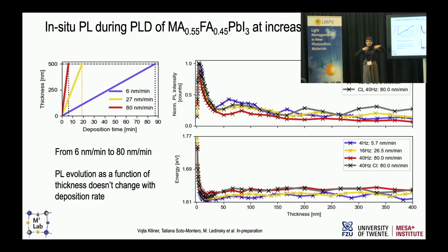So what limits? I think in terms of material quality, it will be the nucleation and growth. You have a lot of nuclei, and if you do it too fast, at some point the grain will be too small. So you might need to play with temperature and other things. Temperature is also a challenge, because if you have temperature and your molecules arrive, they will actually go away. So you might have that process happening. That's why we mainly do room temperature deposition.